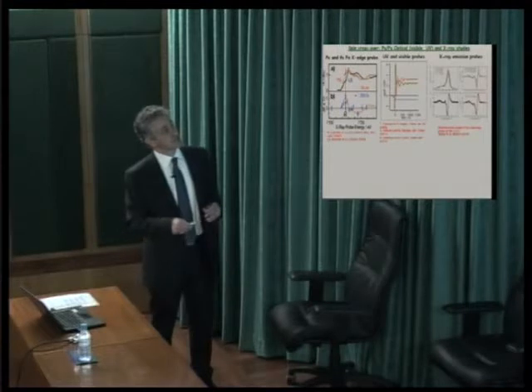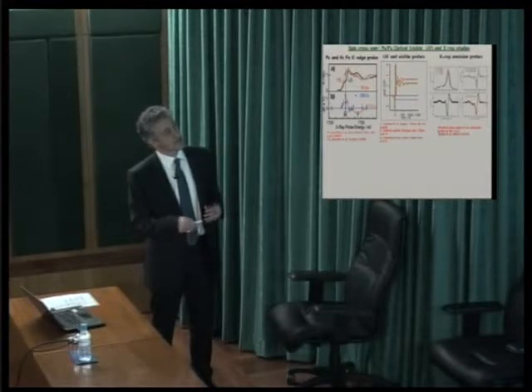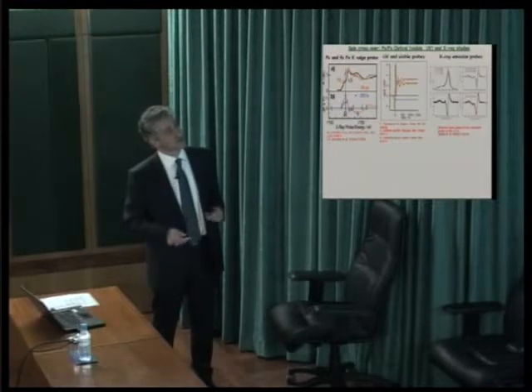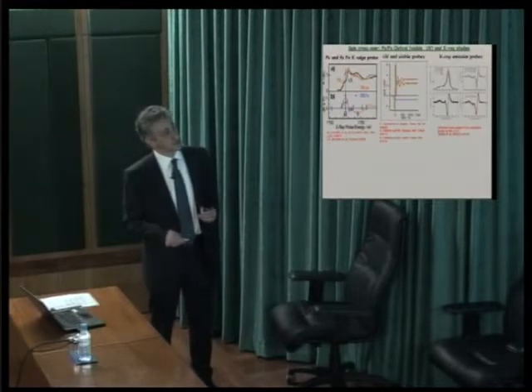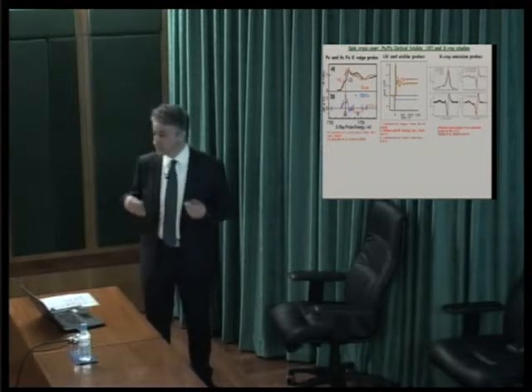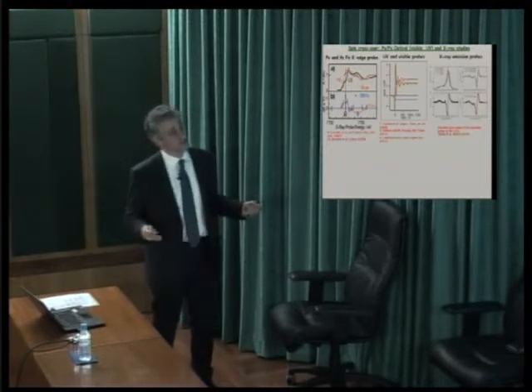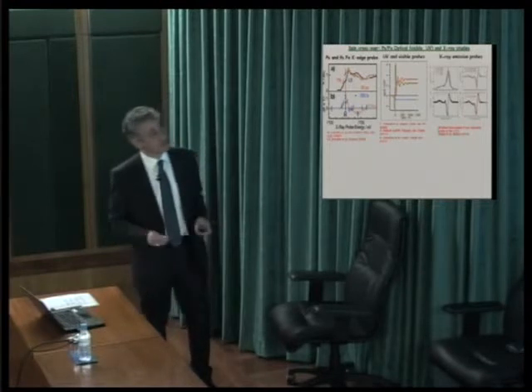These are both picosecond, so the red, and femtosecond transient absorption spectra. These are the spectra before excitation and the spectrum you recover after excitation. This paper was really the first that showed that the high spin state is reached on extremely short timescales, which is very unusual for molecules.